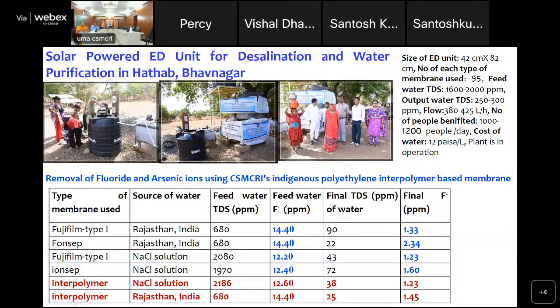This ED plant is also suitable to additionally remove contaminated arsenic and fluoride ions present in the water by electrodialysis. We have tested the performance using a feed water sample from a Rajasthan district, where there was a very high fluoride concentration of 14.4 ppm, and in the final water we could reduce the fluoride concentration to less than 1.5 ppm, which is the limit as per the WHO.